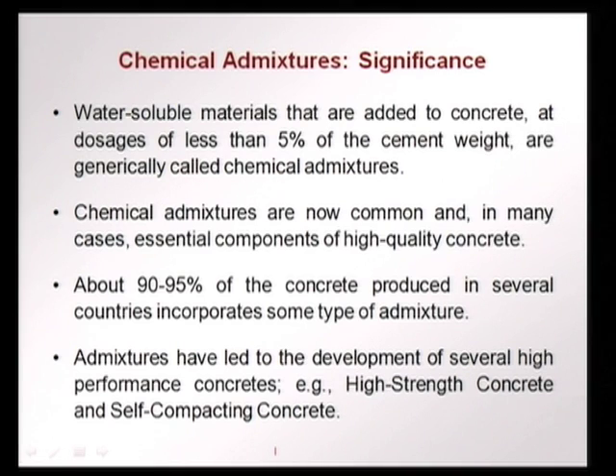Chemical admixtures are materials that are soluble in water. They are added in very small quantities, less than 5% of cement weight. Now these chemical admixtures are very common, and we can say that any high quality concrete made today has some chemical admixture in it. About 90 to 95% of concrete produced in several countries have some type of chemical admixture. Also, when we have high performance concrete like high strength concrete, we already discussed the case of silica fume concrete, self compacting concrete, we cannot make these concretes without chemical admixtures.